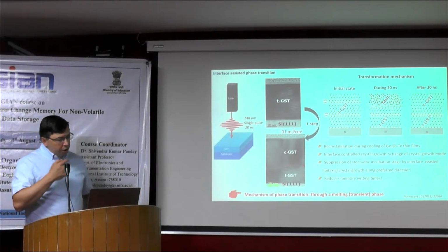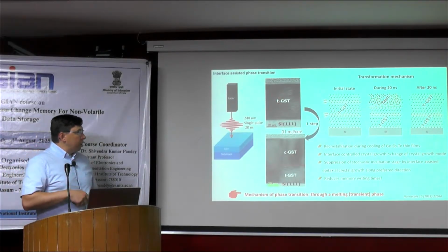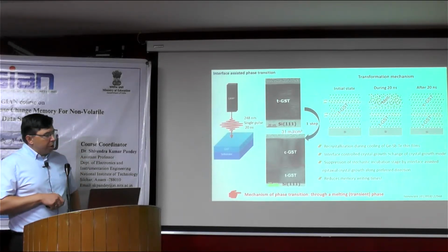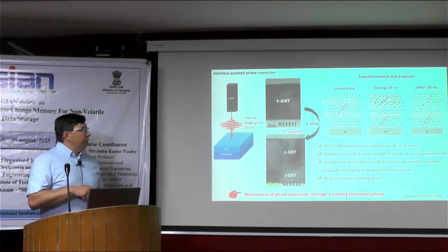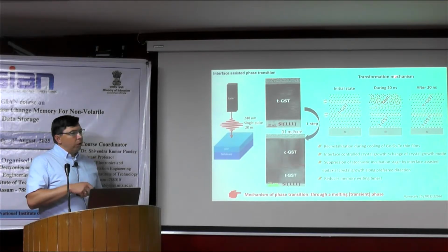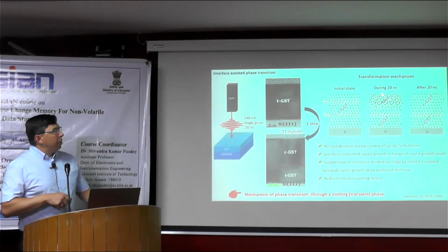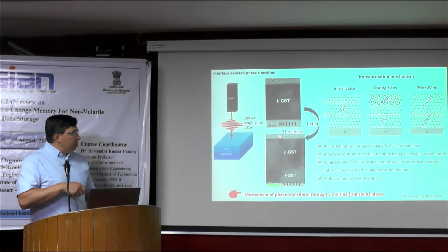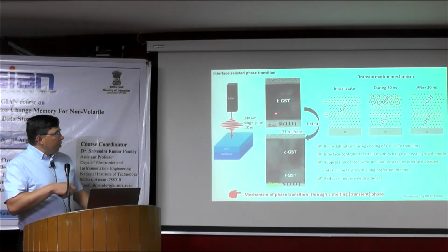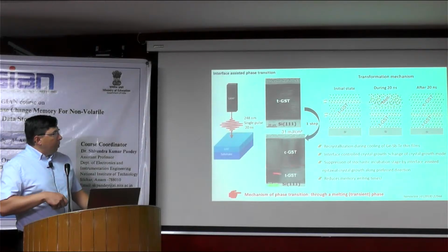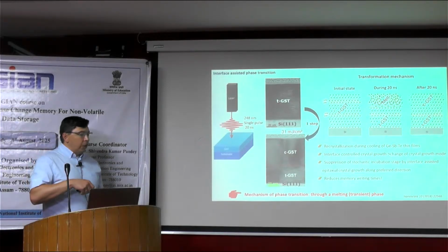But in this case, this transition does not occur through solid-solid transformation. So it's not a crystalline to crystalline transformation. It's more like during this pulse duration of 20 nanoseconds, we melt our system, and during the cooling the system recrystallizes, and then the system goes back to the CGST phase. This image shows this transformation. This is the same thin film, and part of the thin film transformed from TGST to CGST, but by a melt quenching process.